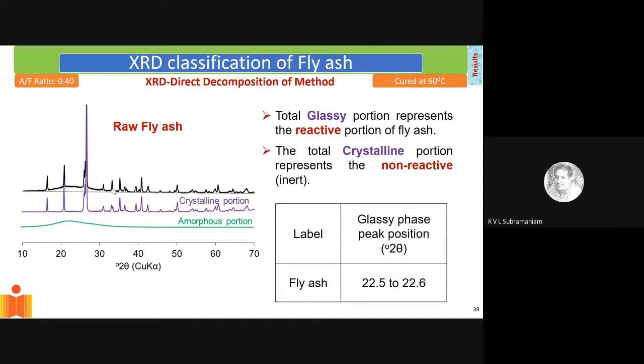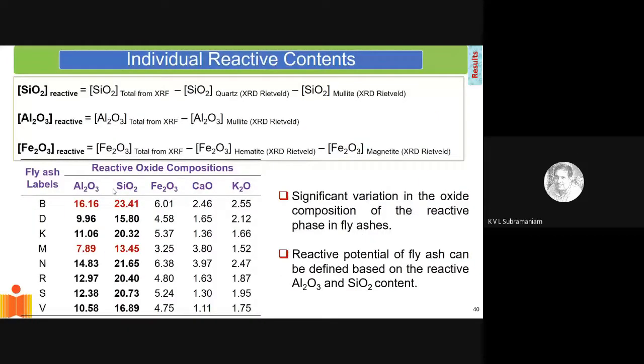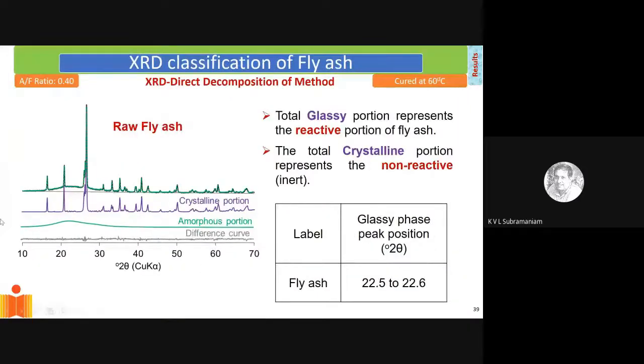Now the reason for doing this will become clear in the next slide, when we start looking at the crystalline forms of the silicon. The crystalline form is primarily quartz, and I'm not interested in quartz because it is a non-reactive form. So those peaks that I showed in the previous XRD signature contain information about the quartz in the material, and we can separate out how much quartz is present. And the remaining part, the broad hump that you see in the XRD signature, is the glassy form. This is where silicon is present in a form which is reactive.